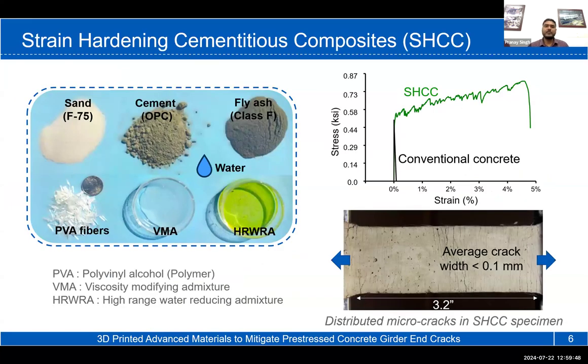Coming to the strain hardening cementitious composite, the material we are proposing for the application is a kind of fiber reinforced concrete, which is optimized to have distributed cracking instead of larger cracks. The constituents are basically the same as any fiber reinforced concrete, and two ingredients, primarily the viscosity modifying admixture and the high range water reducing admixture, will have their ratio and amount calibrated to achieve 3D printability in strain hardening cementitious composites.